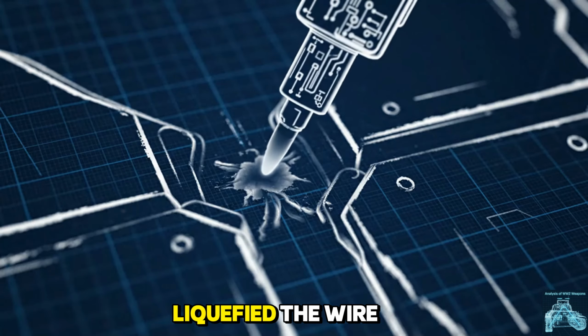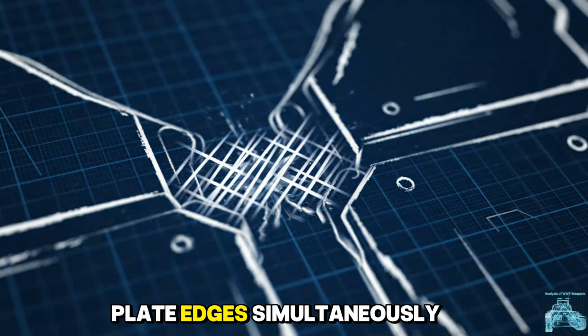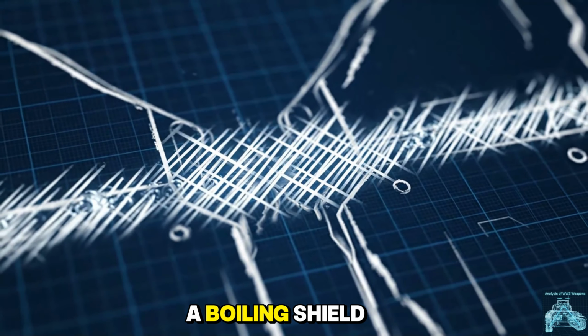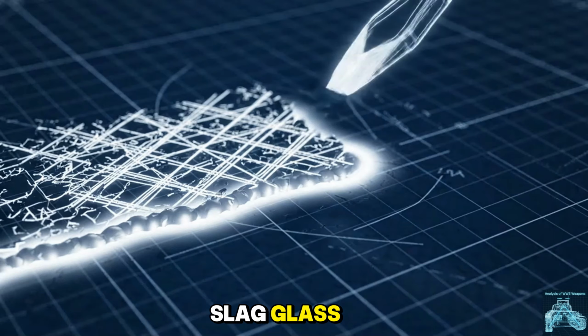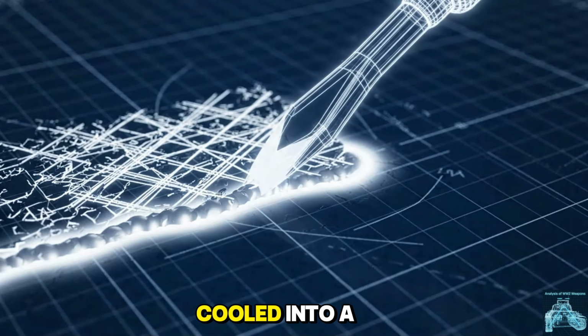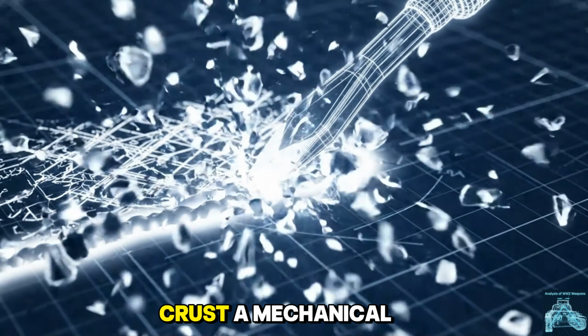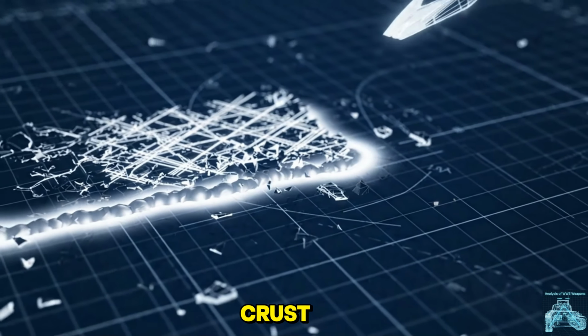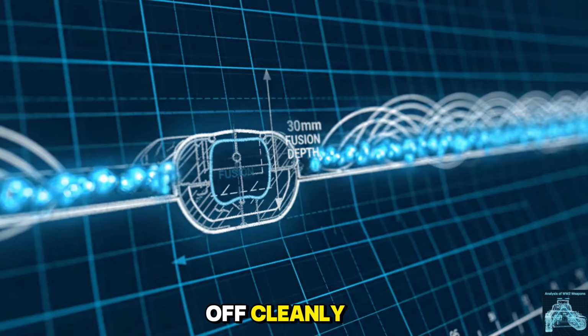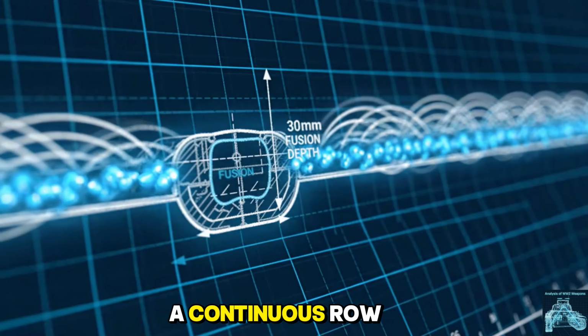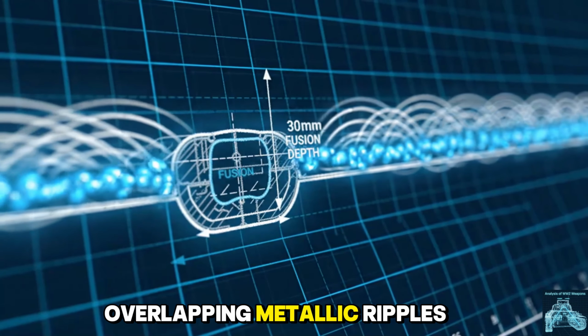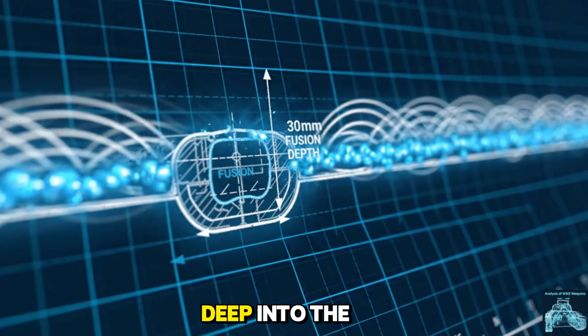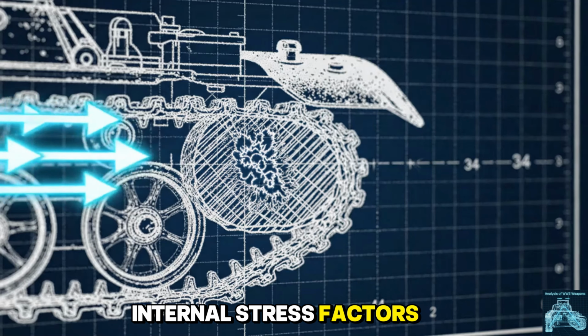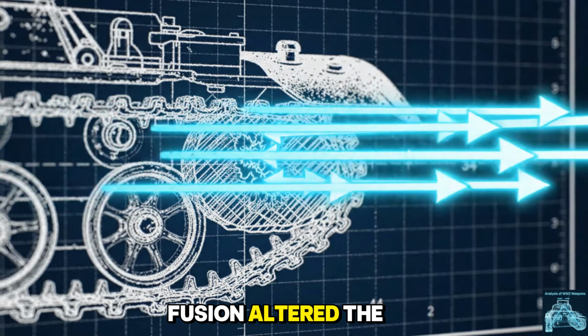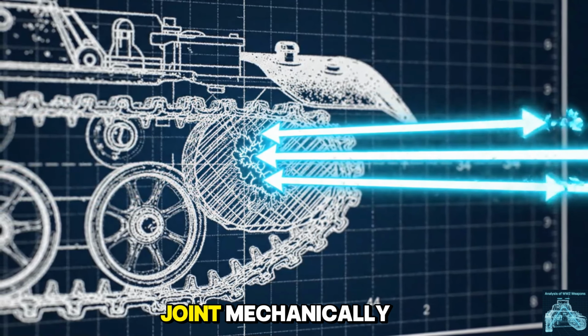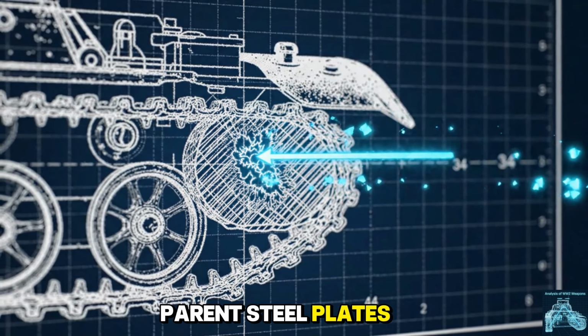The intense heat liquefied the wire electrode and the beveled plate edges simultaneously, blending them under a boiling shield of molten protective slag glass. As the welding head moved forward, the molten slag cooled into a brittle, glass-like brown crust. A mechanical chisel tapped the crust, causing it to shatter and flake off cleanly. What emerged was the finished weld bead, a continuous row of thick, overlapping metallic ripples, fused 30mm deep into the root of the joint. Internal stress factors prove that this automatic fusion altered the crystalline structure, making the welded joint mechanically stronger than the parent steel plates themselves.